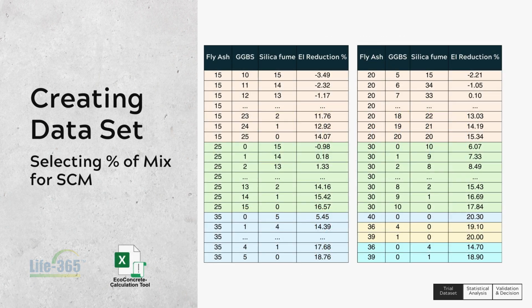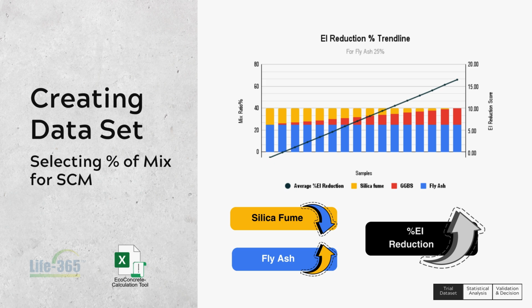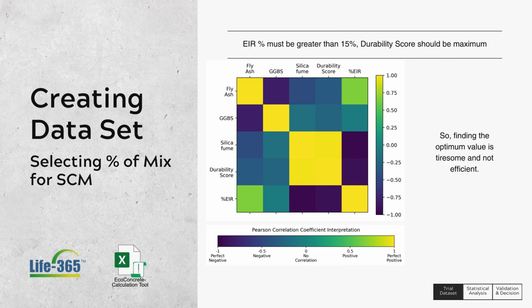Here is the sample dataset that we found using the EcoConcrete calculation tool. Here we could notice that for a specific fly ash percentage, the environmental impact reduction percentage is proportional to the blast furnace slag percentage and inversely proportional to the percentage of silica fume. To understand the relationship between performance indicators, we analyzed Pearson correlation coefficients among variables like fly ash, blast furnace slag, silica fume, durability score, and environmental impact reduction percentage. We observed strong positive and negative correlations, but with so many variables and constraints, manually finding the optimum SCM mix is both tiresome and inefficient.